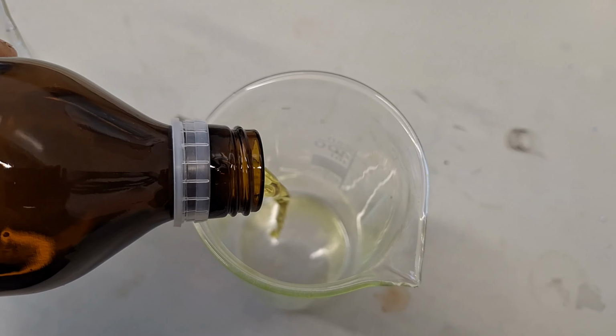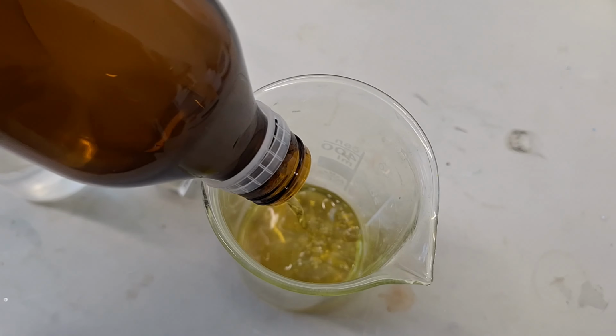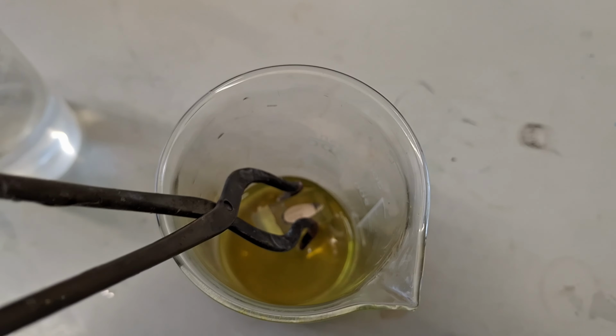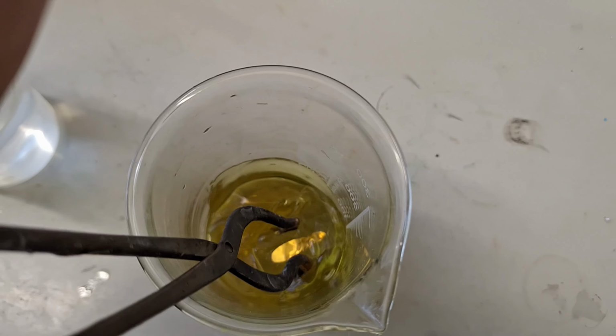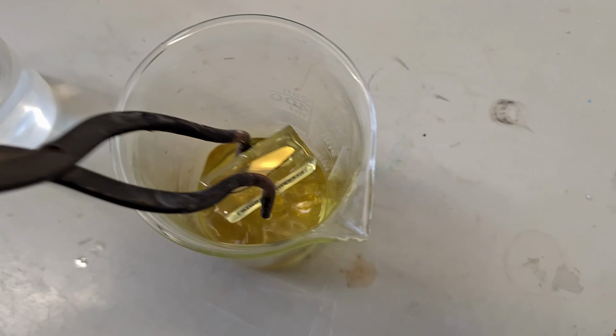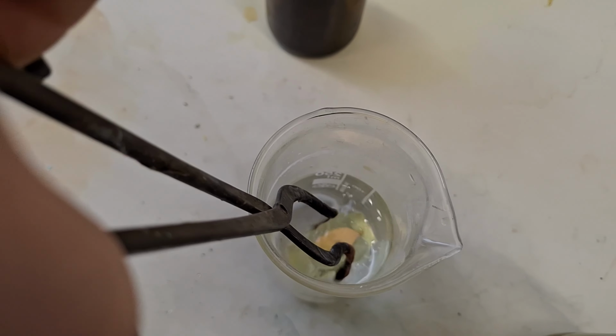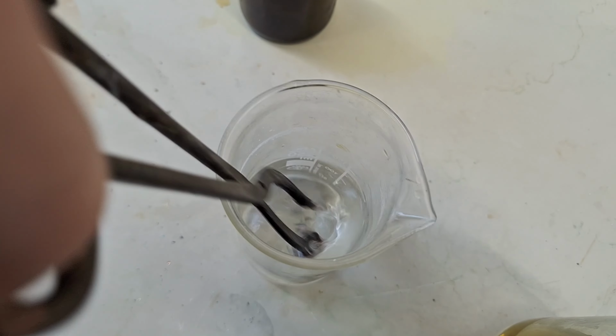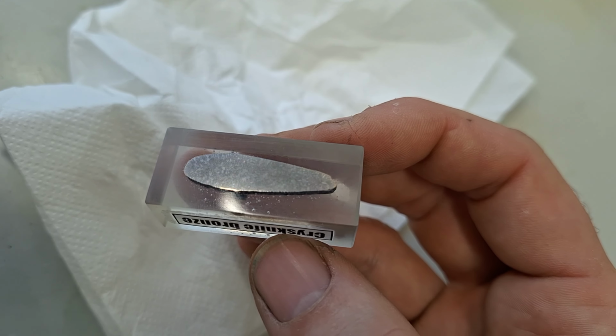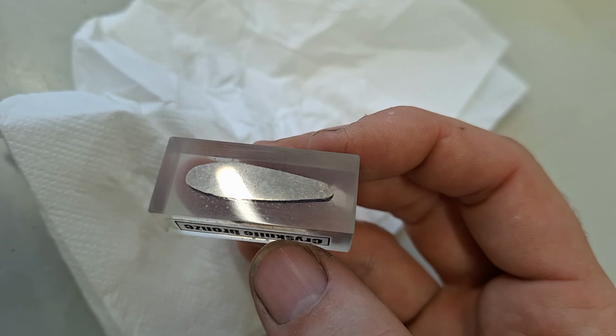Fortunately, we can reveal some additional information through etching. I'm using a ferric chloride etchant mixture. A quick dip and we are done. You can already see that the surface looks different. Just for comparison, here we have unetched, lightly etched and heavily etched bronze samples.